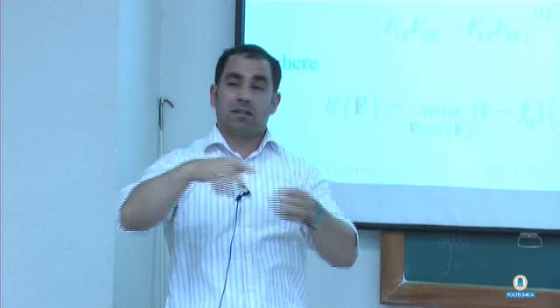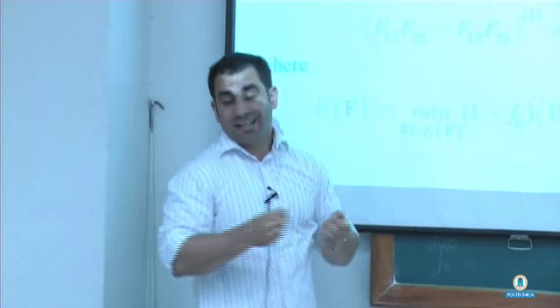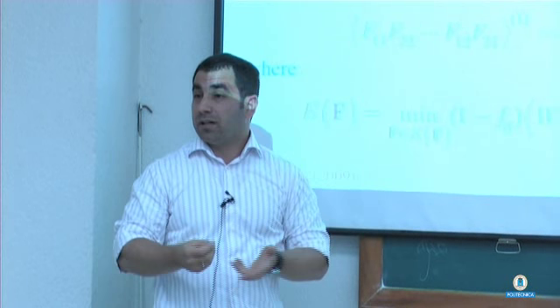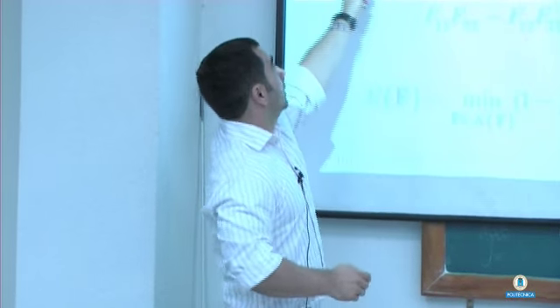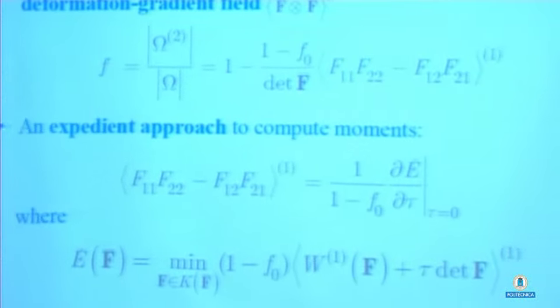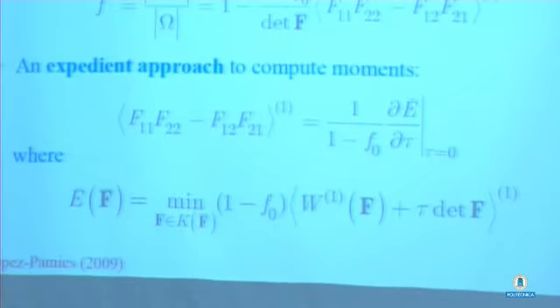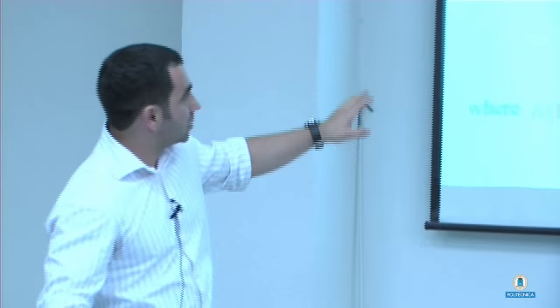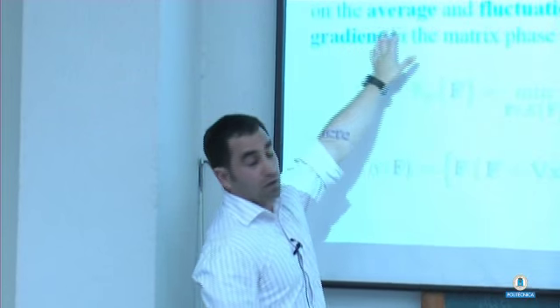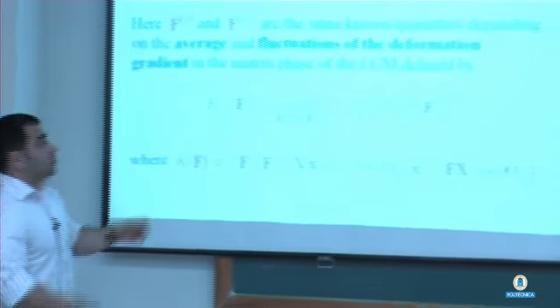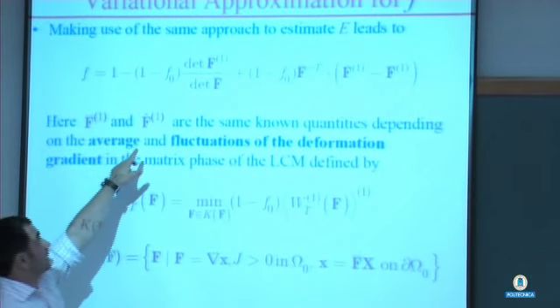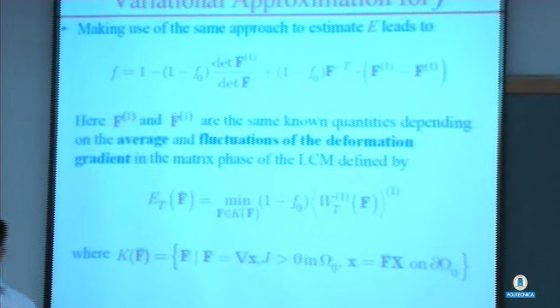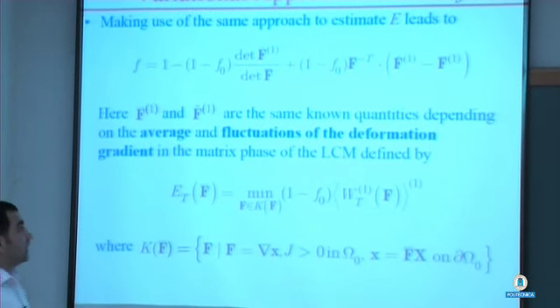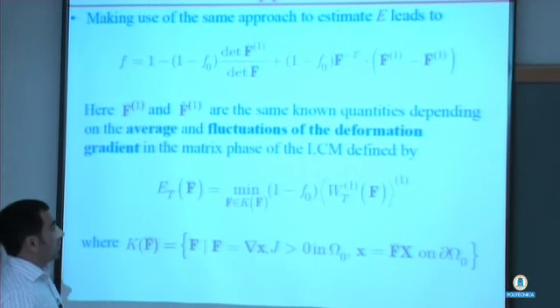And then, of course, you can compute the porosity, because the energy is what? Is basically some traces of the deformation, something about the deformation, right? So is the porosity, so is any average quantity. If you have the deformation gradient tensor, you can compute anything, the total elastic energy, the porosity, whatever you want. And basically this is a layout of a procedure for how to compute these quantities that have to do with microstructure. I'm not going to get into that. I'll show you the formula for the energy. I'm showing you the formula now for the porosity in the current configuration, using this procedure of linear comparison. And you see that it depends on F hat and on F bar 1, things that we already know and we need to use to solve for this total elastic energy. Okay, so now if we're able to solve this problem,